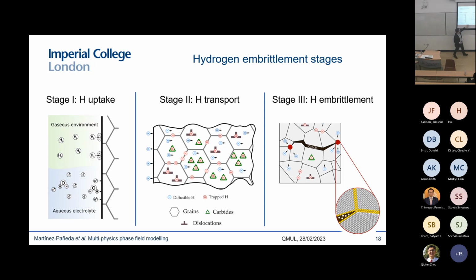Then we need to simulate also the hydrogen transport, so we know that the hydrogen diffuses through the crystal lattice and is also sequestered at certain microstructural sites. So we need to know basically how much hydrogen we have, where and when. And finally, based on this hydrogen accumulation at critical interfaces, we need to be able to predict when hydrogen will trigger the nucleation of cracks and when those cracks will go on to grow and propagate along grain boundaries, for example. So I'm going to discuss each of the steps, starting from the hydrogen uptake and how we simulate those in our finite element models.